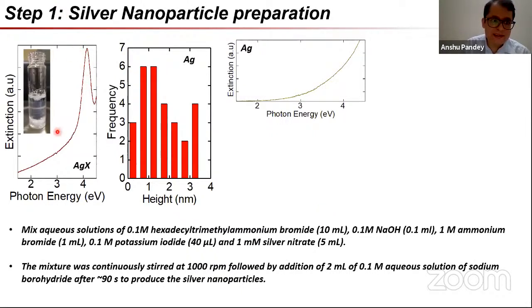So what is done initially is we are mixing up silver nitrate with CTAB. Now there's quite a bit of literature that when you mix silver nitrate with CTAB, you actually get silver halide particles forming. Because of the presence of CTAB, which is cetyl trimethyl ammonium bromide, you end up with silver bromide particles forming most of the time. In our case, we found that we get better results if we have a combination of other reagents added to stabilize this process. We are adding sodium hydroxide, ammonium bromide, and potassium iodide there. So more likely we have a combination of silver bromide iodide. Because CTAB is a surfactant, it prevents these particles from growing arbitrarily large, but rather holds their size to within what will lead to a nanometer of silver.